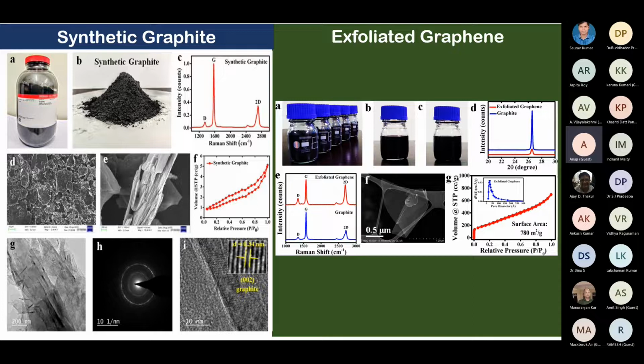and with that intention we started experimenting on this. Our first experiment was bottles B and C, which you are seeing, where we tried to disperse it into DMF and NMP solution. What we found is that after 24 hours of dispersion, the powder is still completely dispersed. So we thought, yes, it definitely might have been exfoliated, that it's indicating.